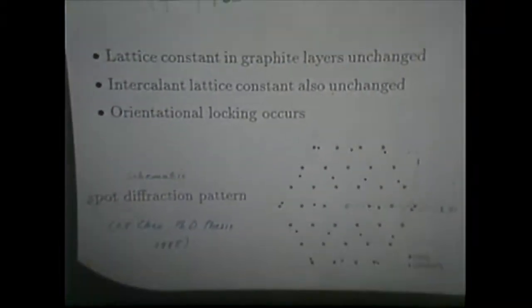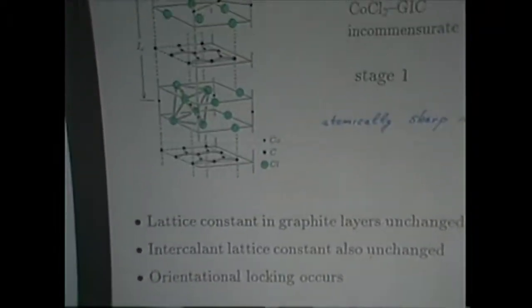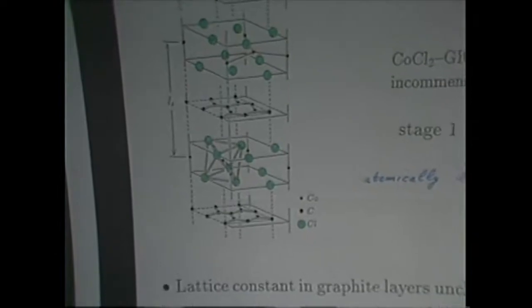Now, getting back to the intercalation compounds, another possibility, when the nearest neighbor distances are totally unmatched to the graphite substrate, then they don't pay any attention to the graphite substrate at all, and they just do their own thing, and they form layers that are just like layers in the host material. Here we see cobalt chloride and graphite. So here's a graphite layer, here's a cobalt chloride tri-layer sandwich, where the lattice constants of the cobalt chloride are exactly the same as they are in native cobalt chloride.